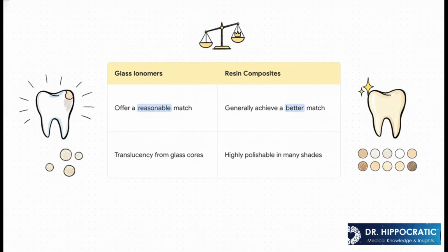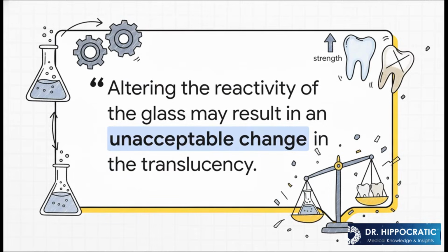But let's be real, when you put them side by side with resin composites, GICs almost always come in second place. Resins are just more polishable and come in a much bigger range of shades. And this creates a massive headache for the manufacturers, and this quote sums it up perfectly. If they try to tweak the glass chemistry to make the material stronger or react better, they often end up making it more opaque and chalky looking, which just kills the aesthetics. It is a constant, frustrating trade-off.